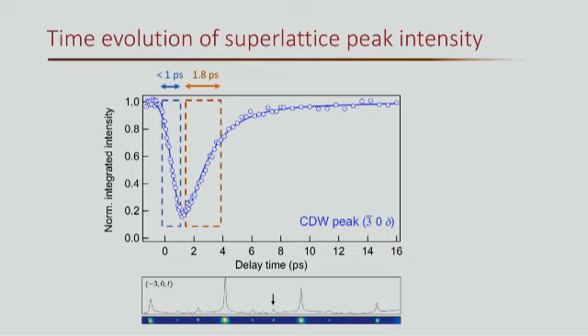Well, we know from diffraction studies that the intensity of a diffraction superlattice peak is proportional to the square of the order parameter magnitude. Basically, a suppression of this intensity means that, for example, the original charge density modulation is suppressed. Yes, that can give us some suppression. We should also consider what happens to the phase of the charge density wave order parameter. If you crank up the calculations, you will find that the phase modulation, which in the cartoon picture is depicted as the charge density wave sliding around, will give you a Debye-Waller factor-like suppression, which is also exponential. So both of these factors contribute to the suppression of the intensity observed here.